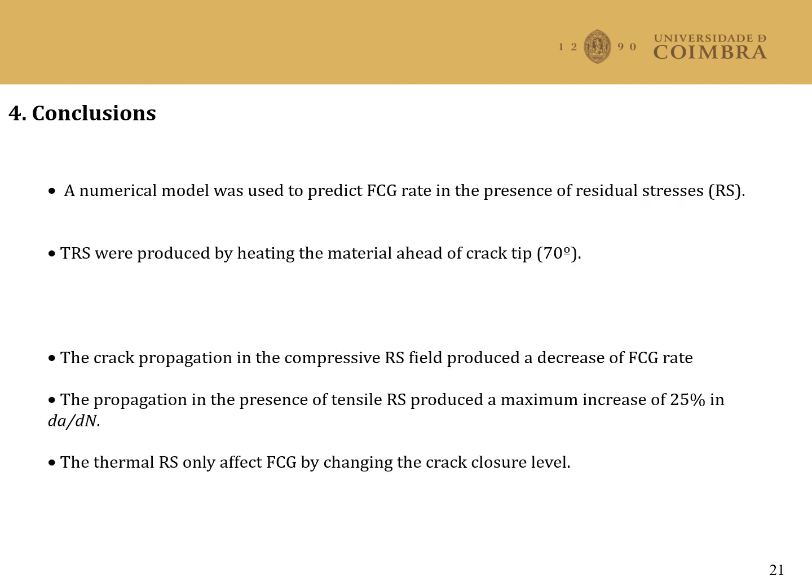The main conclusions of this work are: a numerical model was used to predict fatigue crack growth rate in the presence of thermal residual stresses, which were produced by heating the material ahead of the initial crack tip position. The compressive residual stresses produced a decrease of da/dN, while the tensile residual stresses produced an increase of da/dN, as could be expected. Finally, the thermal residual stresses effect was clearly associated with crack closure phenomena. Thank you for your attention.